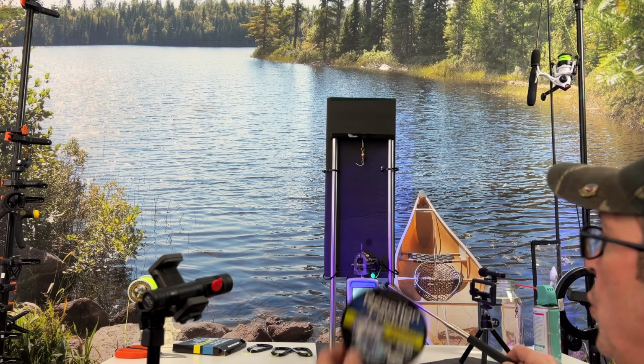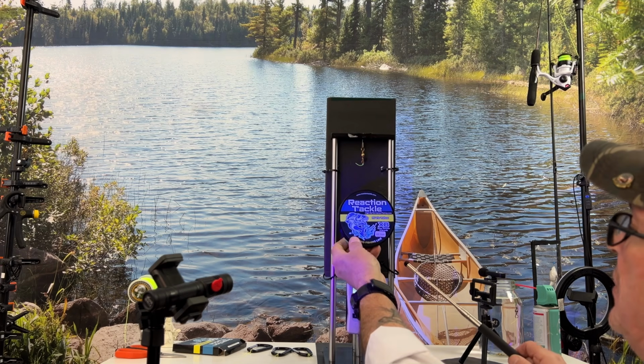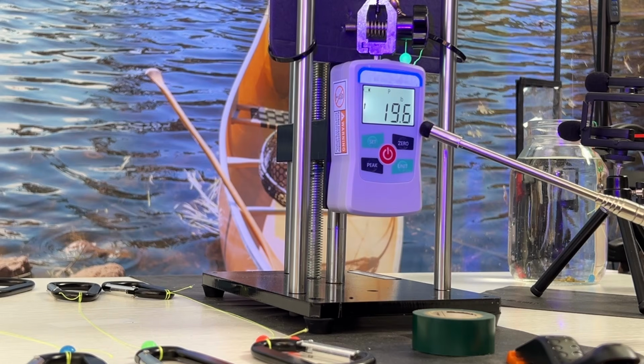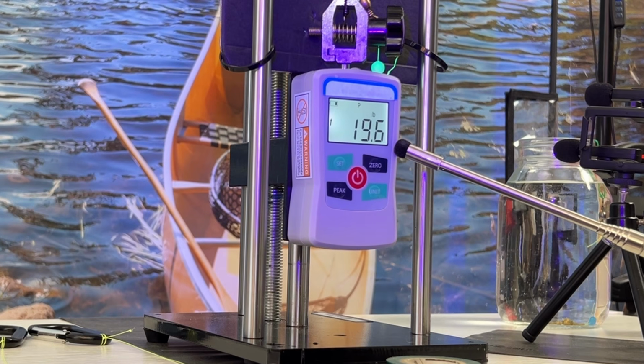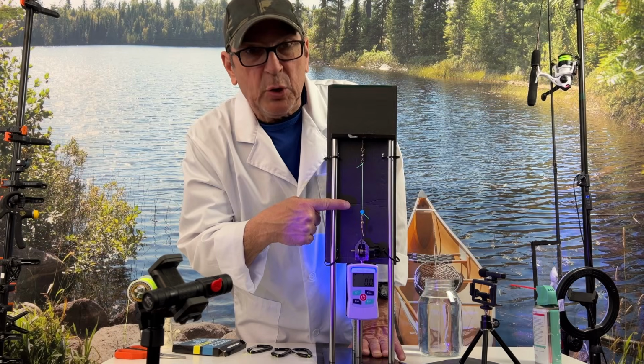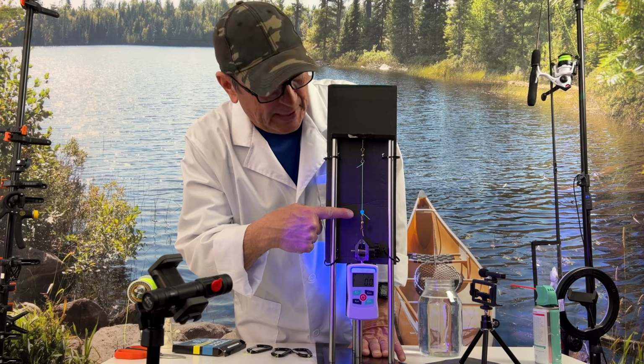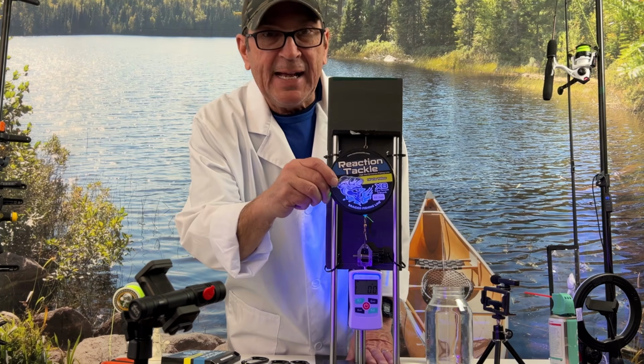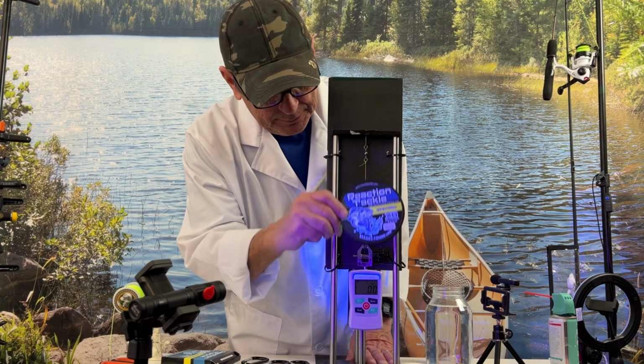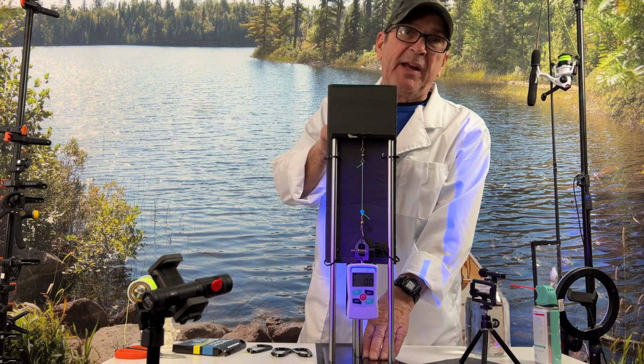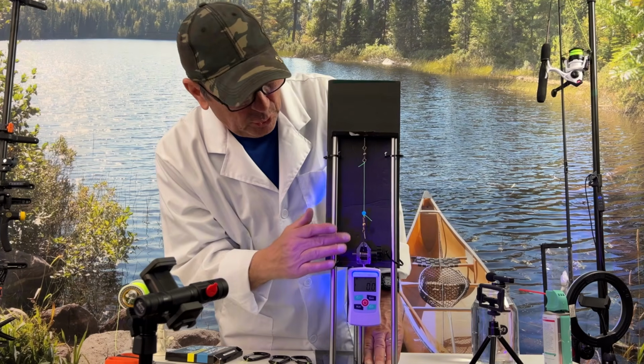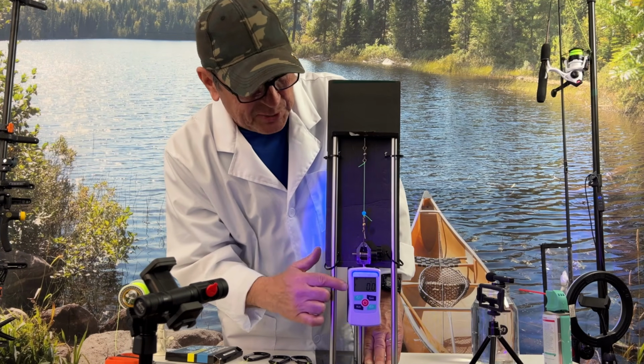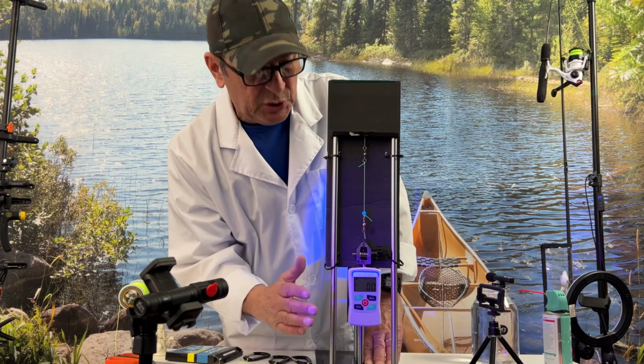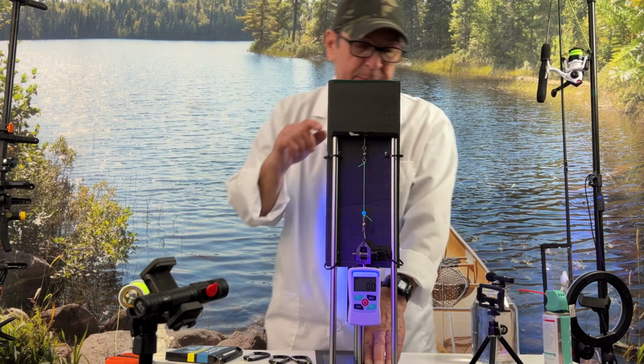Okay, test 2 of the wet braided fishing line, 20-pound braided fishing line from Reaction Tackle, reached a tensile strength of 19.6 pounds. Here we go with test 3, represented by the blue fishing bead. Reaction Tackle, 20-pound braided fishing line. In order for this fishing line to pass, this meter has to reach at least 20 pounds to start with. Here we go.